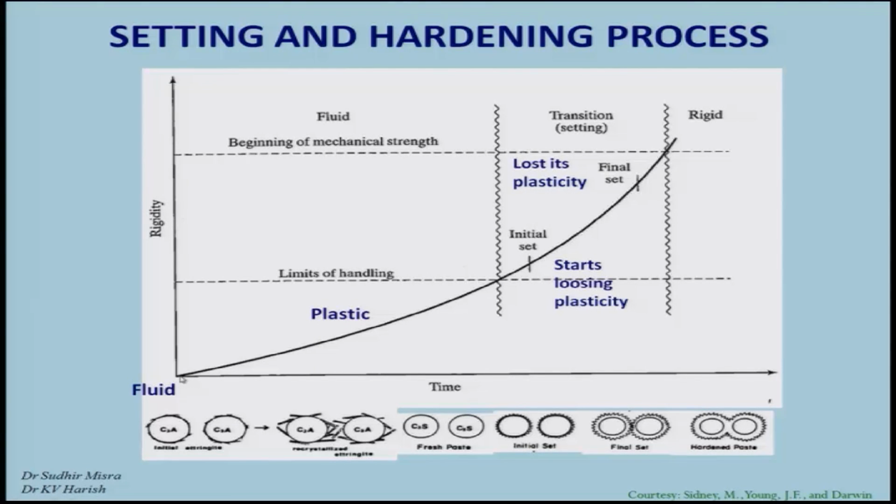As soon as water is added, the system becomes fluid, then goes to a plastic stage, and from the plastic stage it goes to the initial set, which defines the limit at which the system starts losing plasticity, and then it reaches the final set where the plasticity of the system is more or less completely lost. In other words, the system has gained substantial rigidity so that it can start taking loads.